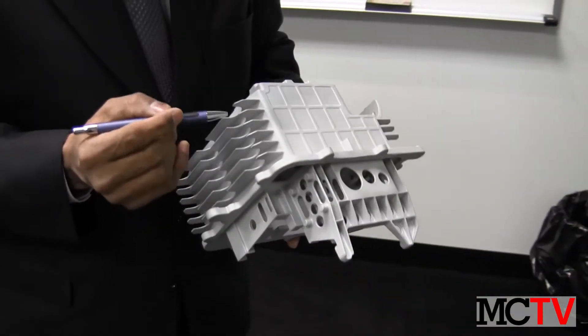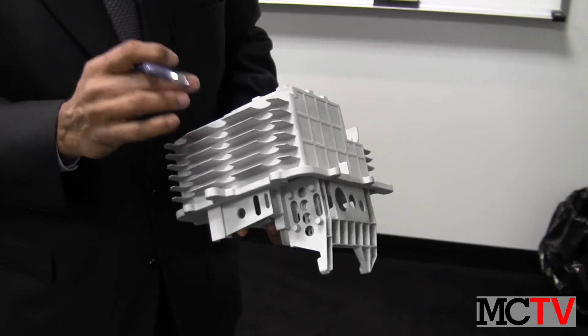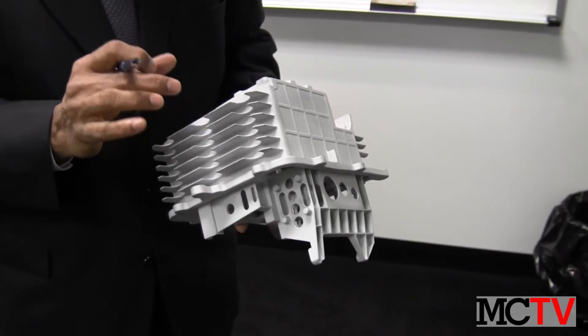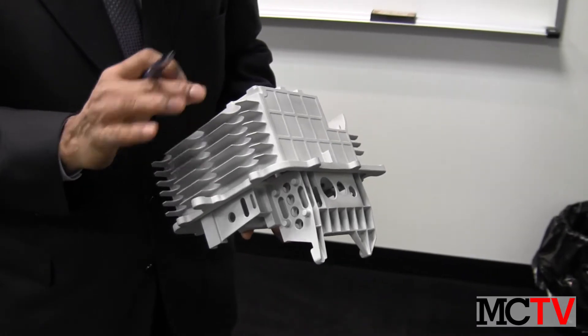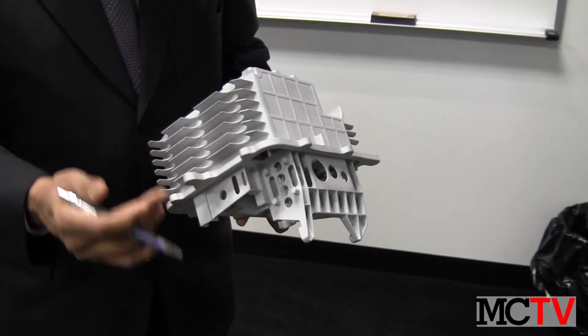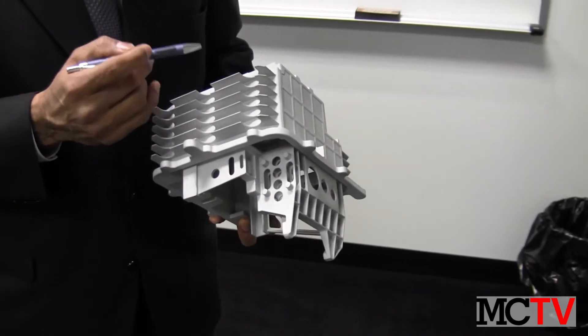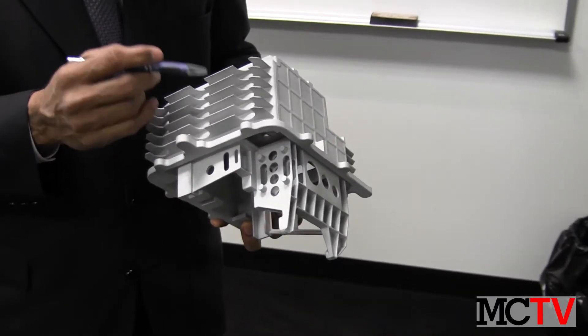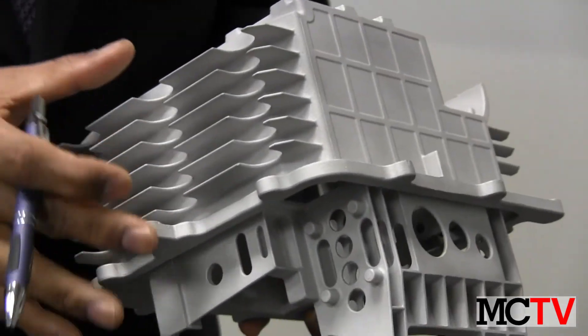Also, this being an electronic housing, the as-cast cooling fins are an integral part of this particular design, which helps extract the heat away from this electronic housing. And these are made with practically no draft or very minimal draft conditions, which is possible with an investment casting process.